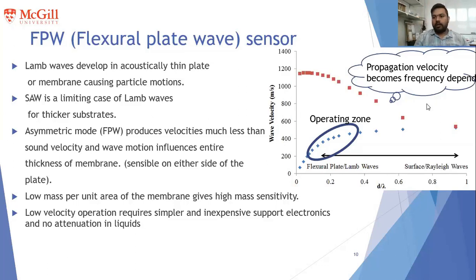When the thickness of the substrate becomes very small compared to the wavelength of the IDT pattern, the acoustic velocity becomes much lower. It becomes a function of the thickness to wavelength ratio. This is a special case of Lamb wave, called flexural plate waves. This very low acoustic wave velocity is exploited in flexural plate wave sensors, which have very good mass sensitivity and also call for low frequency operation, which in turn reduces the operational cost as well.